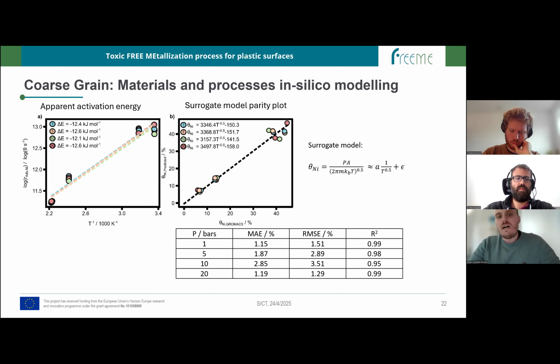apparent activation energy. To do so, we used an extremely common and easy Arrhenius relationship in which we have calculated the velocity or the rate of adsorption of nickel on the ABS, and then we can represent this in a 1 over T plot, and then the slope would correspond to this apparent activation energy that Guillaume was mentioning before, but in the case of atom diffusion, in this case it would be adsorption.